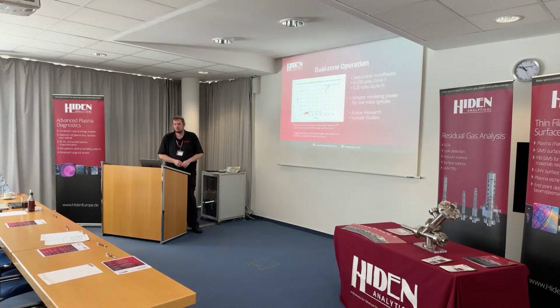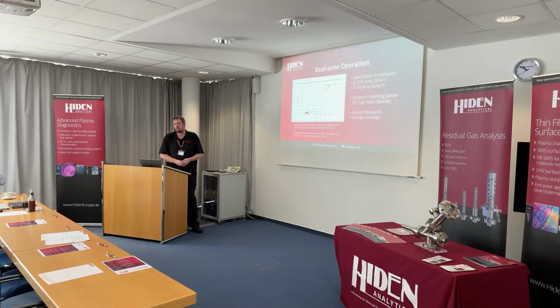But if you measure in zone 1, there is no difference in the sensitivity to different mass numbers, right, whether we measure smaller or higher mass numbers? Yeah, you get mass-dependent transmission. The transmission does fall off at the higher masses. That's a well-known thing. I think we publish a rough table of that, and there's a relationship there. That would be something you would do afterwards. It only matters if you're doing quantitative measurements. If you're doing relative measurements, the mass is sort of independent, and you don't have to take it into account.